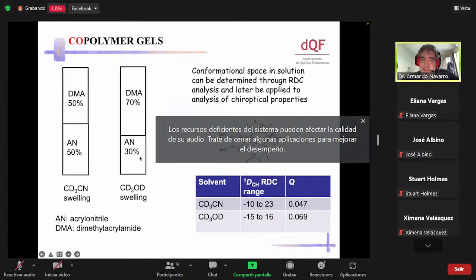So we wanted basically to get something for acrylonitrile. This was difficult to do using just a monomer for the polymerization. But we found that mixing monomers gave us a polymer of the appropriate polarity. So we mixed dimethylacrylamide with acrylonitrile.